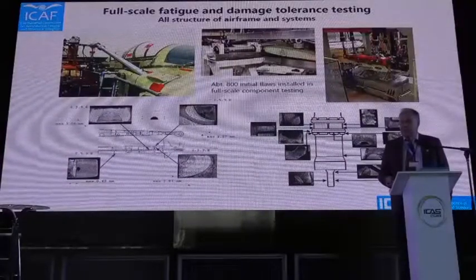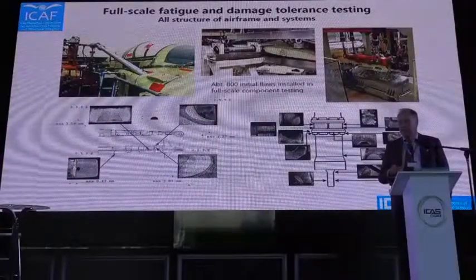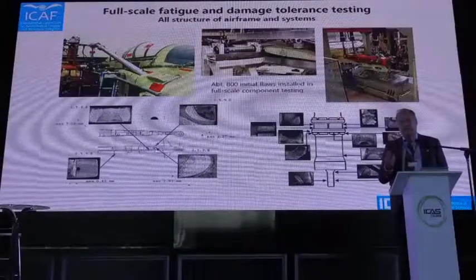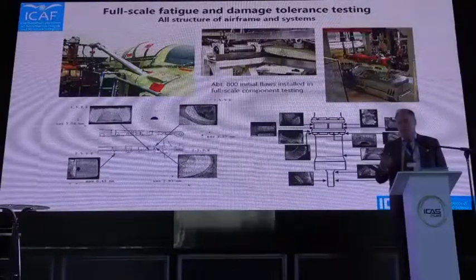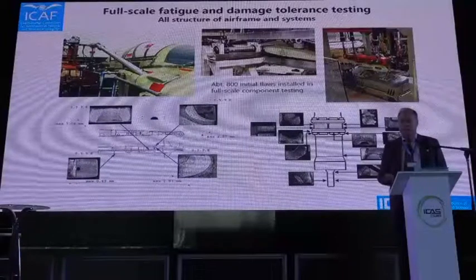Full-scale fatigue and damage tolerance testing is done for each and every new aircraft. Typically, you do full 2 fatigue lives first, then you introduce flaws at critical locations and do up to 2 more lives, and then eventually residual strength tests.